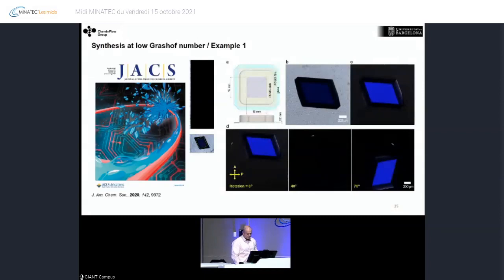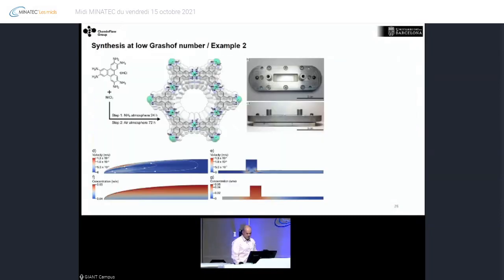We were also very happy to get the cover of the journal. And something that we are focusing on now is also 2D materials and trying to synthesize them in these conditions. So here, an example, this is a very well-studied conductive MOF, or 2D MOF. And it is very difficult to generate very long, thin films with this material. Normally people are using pelletization to get pellets and do the measurement. It's very difficult to grow them over long distances.